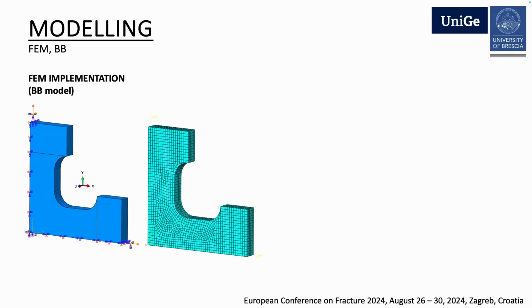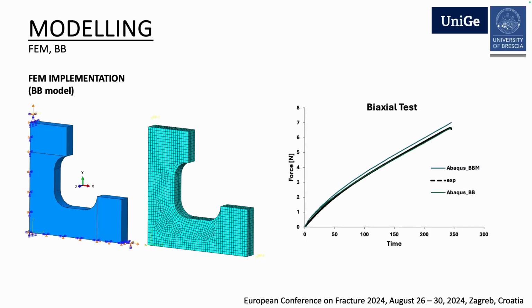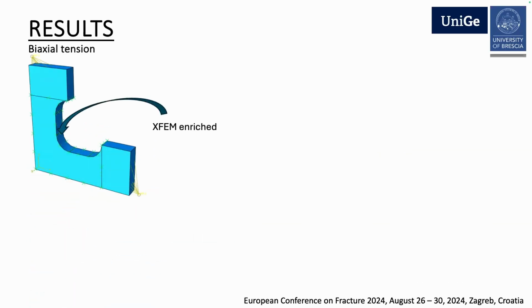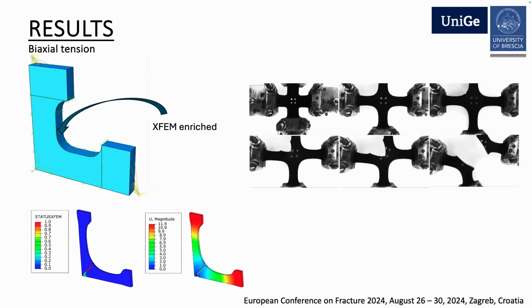So what we are trying to do now is to implement these models within finite element simulation. In particular, we took the equibiaxial test as a test bench. And actually, it seems that these models work fine. Here we can see the prediction of the force against time for the Bergstrom-Boyce model. And BBM stands for a modified version where the Mullins effect is taken into account, but you can see there's basically no difference.